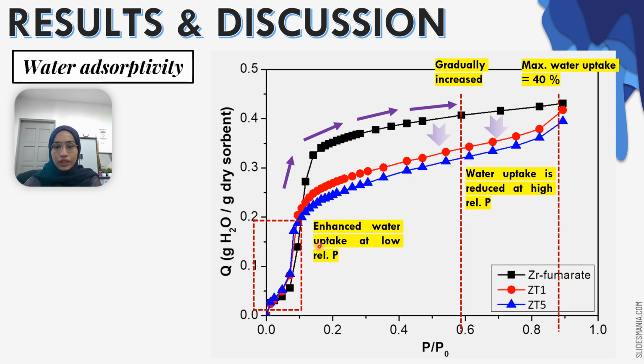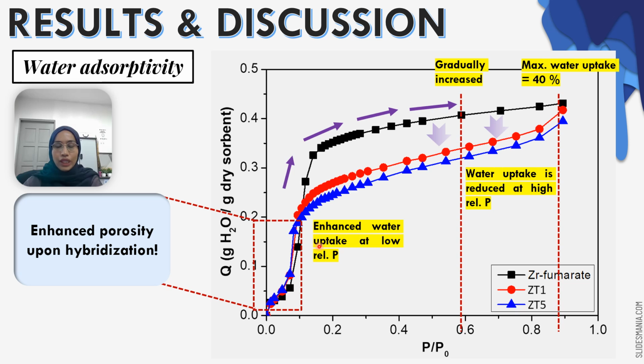Okay, so what actually happened here? The enhancement of water uptake at a low relative pressure might be due to the enhancement of porosity upon hybridization, meaning that after we hybridize the MOF with the TiO2 nanosheets, the porosity of the material is improved. When the porosity of the material is improved, the water affinity is also improved. That's why we can see the enhancement of the water uptake of the nanohybrids.